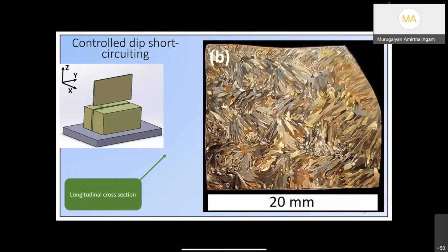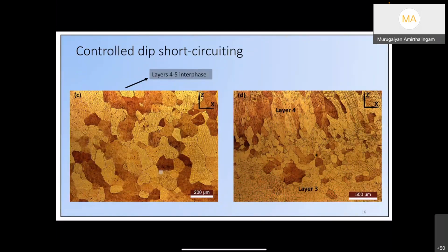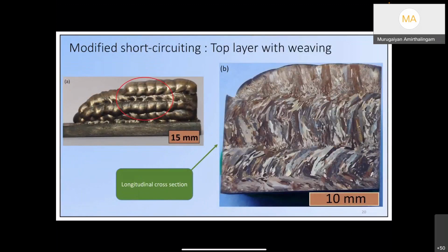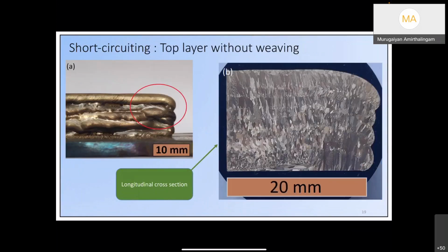If you go deeper, if you take the cross section like this, you see whenever a dipping event happens, more nucleation happens because of the undercooling provided by the wire dipping. In the previous case, growth goes from the substrate or layer bottom along the heat extraction direction. And we break that growth by this dipping event. Then the change in the temperature gradient also leads to bidirectional growth, from bottom to top and then top to bottom, so that now we get a very fine equiaxed microstructure, what you see in this slide. Good, so that's what we can achieve by various strategies.